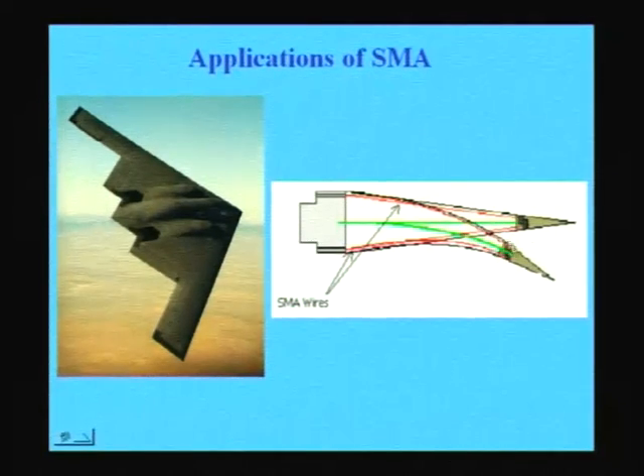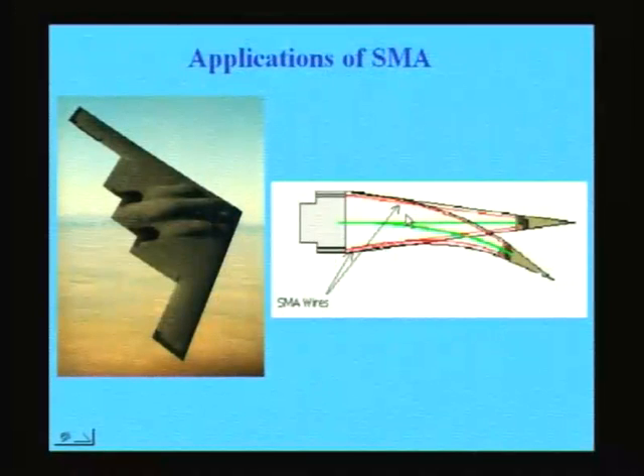So nowadays people want to use shape memory alloy wires, where the shape memory effect can lead to movement of these fins in a downward or upward direction depending on the loads. For example, the moment you give an electrical signal here, and that electrical signal transmits to it, that induces some kind of pressure on the shape memory alloy. Then immediately it transforms to a martensite, or if it is already in the martensitic condition, it transforms back to the austenitic condition. So by the change of transformation from austenite to martensite, just by a phase transformation, we can have the whole fin moving either upward or downward. This is one of the applications.